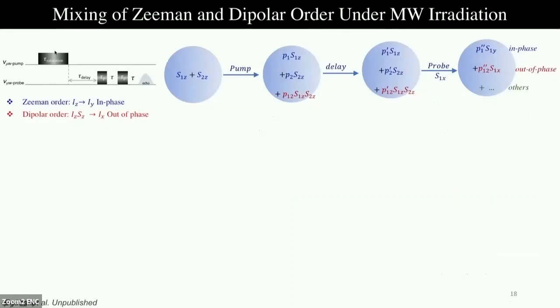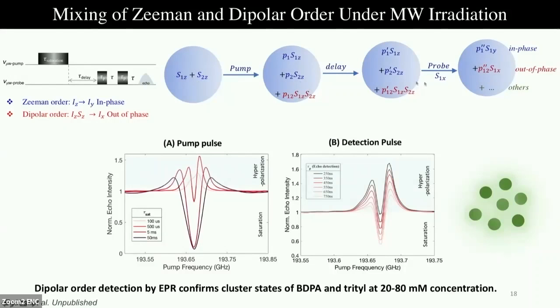Our experiment is something like this, where we first pump, then we have a delay, and then we probe. So basically, we have this schematic where we have Zeeman order, and then with the pump, we are creating the dipolar order. During this delay, there can be different relaxation dynamics of the Zeeman order and dipolar order. And with the probe, we convert these orders into coherences, which would be in phase and out of phase. So by controlling the spin parameters, it's possible to change the relative amount of saturation or the Zeeman order and the dipolar order, something which we could confirm experimentally.